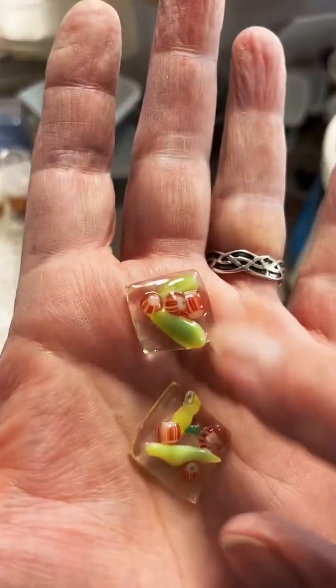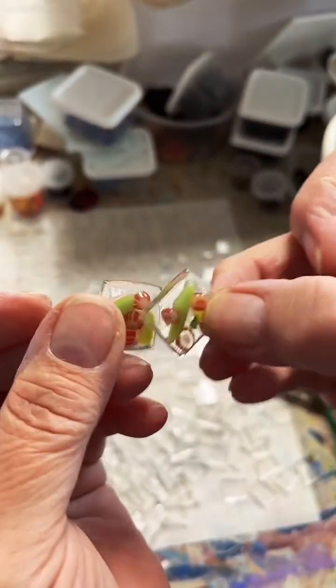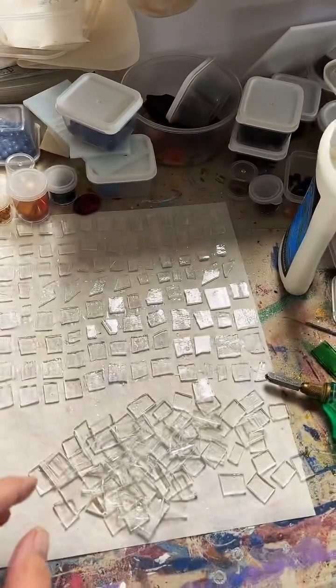And they are going to come out. These are little peppermint twists that I made in the kiln. And they come out fused. They're really sturdy glass, even though it's glass, because I anneal these for an hour, which is I let them soak at 950 degrees for 1 hour.